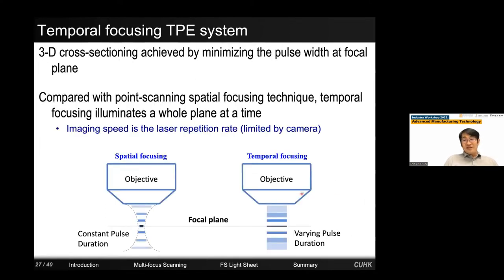Okay, so this slide shows an image comparing with the conventional point scanning, or so-called spatial focusing idea. The energy of a laser system is focused to this point, and by raster scanning the point, material is processed. But along the light path, the pulse width remains constant. In a temporal focusing system, we do not focus the laser beam. The laser beam diameter is adjusted to be equivalent to the processing area. As you can see, along the light path the pulse width is varying instead, and only at the focal plane the pulse width is narrow and can have a multi-photon effect.